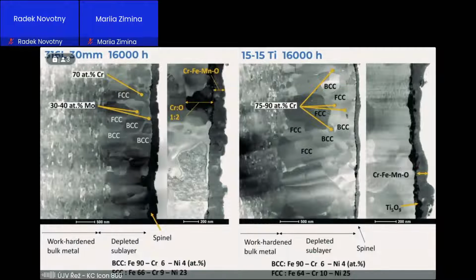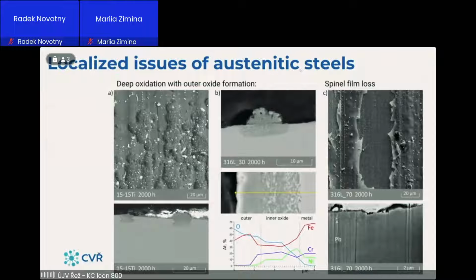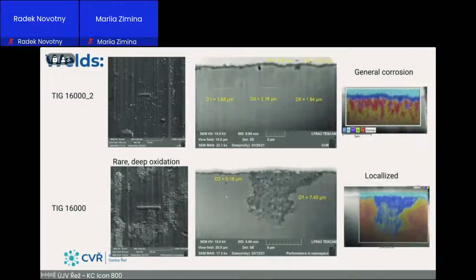That may affect some long-term behavior, but 16,000 hours is not enough. So there are some localized issues that are connected with depletion of this fine grain layer created by machining. When this corrosion or oxidation gets through, we have accelerated oxidation that is connected with outer iron oxide formation that's similar to ferritic-martensitic steel. The weld behavior is very similar to normal base material. It's protected by a very thin oxide layer. There is a depletion layer underneath with this nickel-rich FCC and iron-rich BCC phases with some localized deep oxidation.